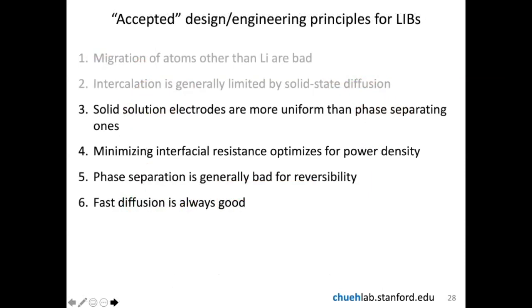Solid solution electrodes are more uniform than phase-separating ones. This is not the case for lithium iron phosphate, especially when the current is high. Minimizing interfacial resistance doesn't always optimize for power density. In the case of lithium iron phosphate, if you have a sufficient interfacial resistance, you can actually use the voltage drop to remove the heterogeneity due to phase separation. Five, as was noted in the original paper by John Goodenough, phase separation can be a problem, but you can get rid of it by engineering the surface reaction kinetics. So with that, let me conclude and thank you very much for listening.